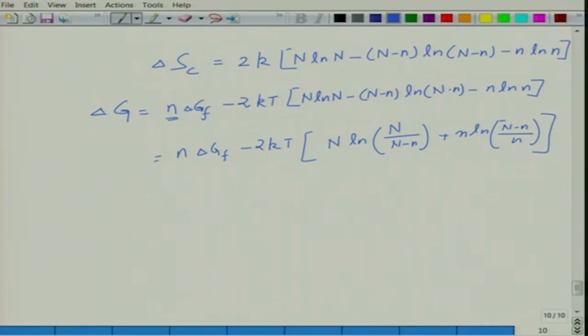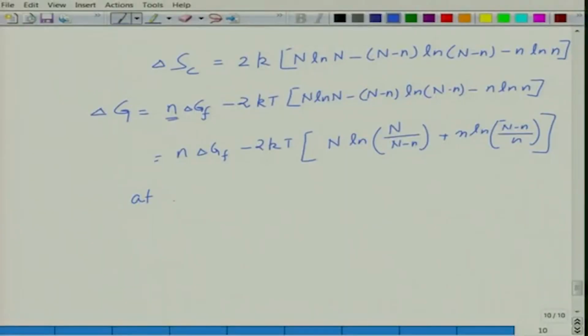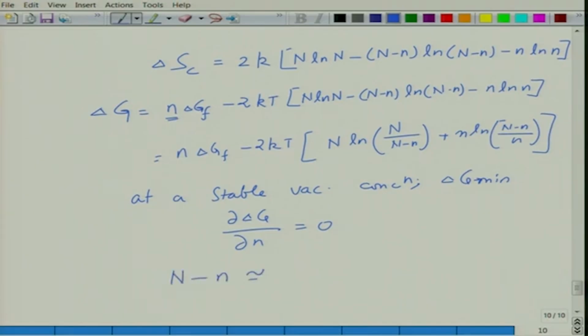Now what you have to do is that if vacancies were stable defects, then at a certain concentration the free energy would be minimum. That means at a stable vacancy concentration or defect concentration, delta G should be minimum, which means del of delta G divided by del of n must be equal to 0. We must get some solution at that point, and we also assume capital N minus small n is almost equal to N, because small n is very small, of the order of ppm or even lower. So if we make that approximation, then we can work out this as small n divided by capital N, which is equal to exponential of minus delta Gf divided by 2 kT.